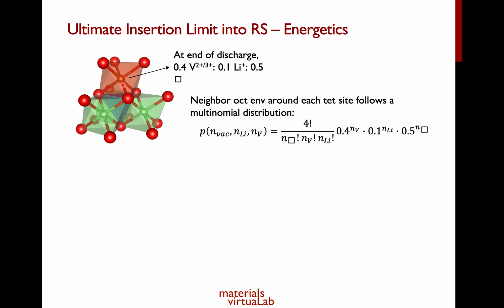So if we think about our disordered rock salt at the end of our insertion process, which is LiV2O5, okay? Remember, our octahedral site is 40% occupied by vanadium 2+ or 3+. It is 10% occupied by lithium plus and 50% occupied by vacancies, okay? So if we think about the octahedral local environment around each tetrahedral site, we can actually construct what the distribution of this tetrahedral site is going to be, okay? So the probability that you have a certain number of vacancies, lithium and vanadium around a particular tetrahedral site is given by this multinomial distribution, okay?